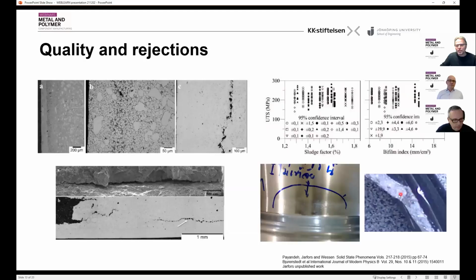And what you will see is that if it fractures, oxide will go all the way through. So it affects all the quality of the part. There are a number of ways we try to characterize this, and this is something that Murat will cover a little bit more later. But there is a difficulty in understanding what is a good melt and what is a bad melt. But we know that during the melting process, if you have a lot of material loss, you generate more slag and there's a higher risk for it to enter the system.